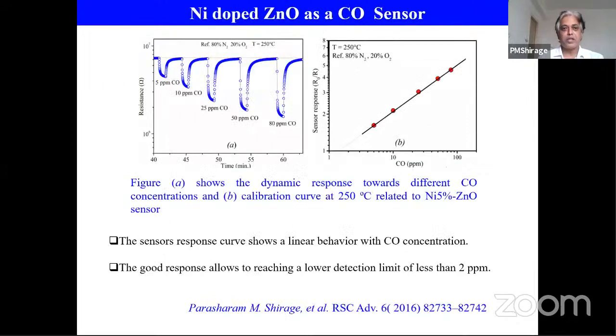In order to measure this sensing property, we have to measure either the capacitance or resistance. For example, I utilized resistance measurement. I measured the resistance of the sensor with different concentrations of exposure to CO, and with increasing concentration of CO, the resistance is decreasing. It means the sensor is working, and it is giving very good response and recovery time. The response time is about 10 seconds, and the recovery time is about 15 seconds. And we can measure the calibration curve, which is nothing but the change in resistance with the change in concentration when we expose the sensor to different concentrations of CO.